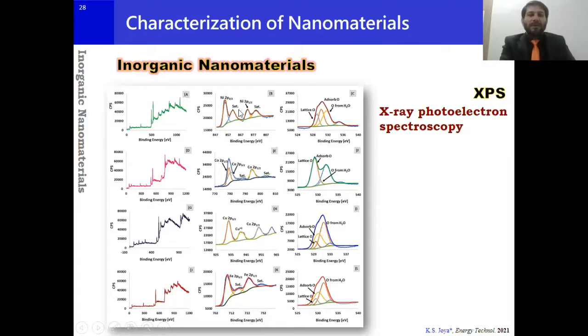In this case, you can see it's nickel XPS, nickel 2p, this is cobalt, this is copper, this is iron. And of course because these are all oxides, metal combined with oxygen is there, so you can see the different peaks for each oxygen, whether it's free oxygen or adsorbed oxygen, or even which kind of metal the oxygen is bound to. Let's say the metal is present in +1 state, +2 state, or in some cases it is 0, which is pure metal.